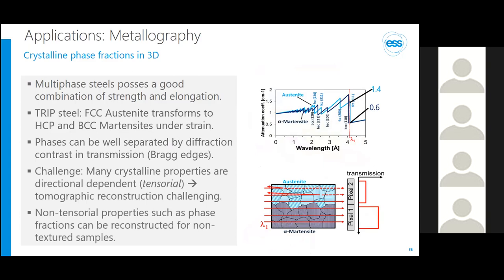So this all sounds very great, like we have a killer method, but life is never perfect. One main challenge lies in the fact that since many crystalline properties are directionally dependent, as I told you before, a three-dimensional reconstruction is not always possible. And this not only concerns neutrons, of course, but also electrons or X-ray methods. If the sample, however, has grains that are almost randomly oriented, in other words texture-free, then non-tensorial properties, such as phase fractions, as I will show you, can be reconstructed by common tomographic reconstruction methods, such as the widely utilized filtered back projection algorithm.